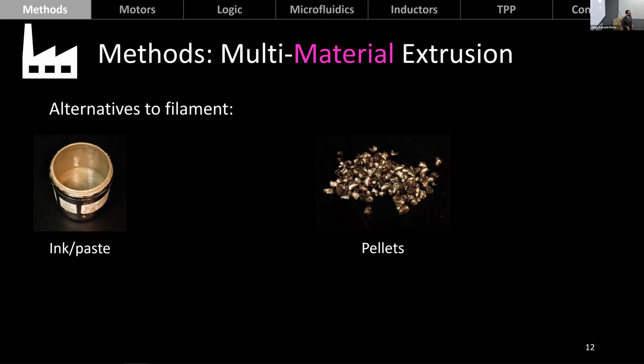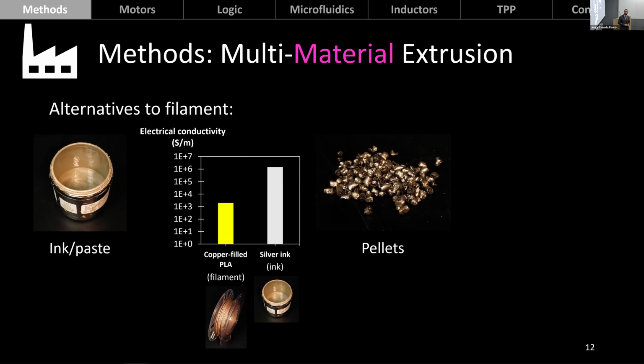Now, these materials are not necessarily meant for material extrusion additive manufacturing. In particular, the ink is meant for screen printing or other electronics manufacturing, and the pellets are meant for injection molding, so a more traditional manufacturing method. But if we are able to adapt our 3D printing system and make it able to use these materials, then we will be able to access much higher performances. And to illustrate that, here's a comparison of the electrical conductivity, which we would hope to have the highest value, between the conductive filament that I mentioned in the previous slide and this silver ink.